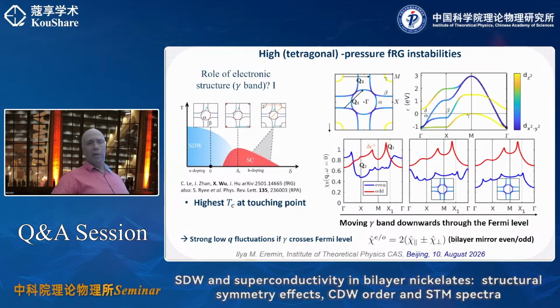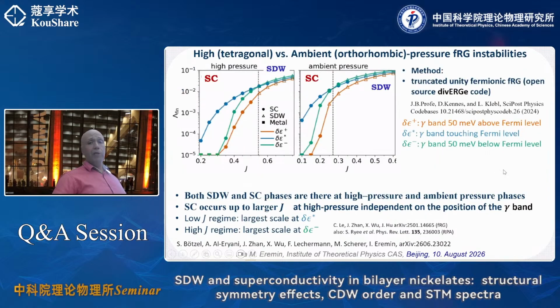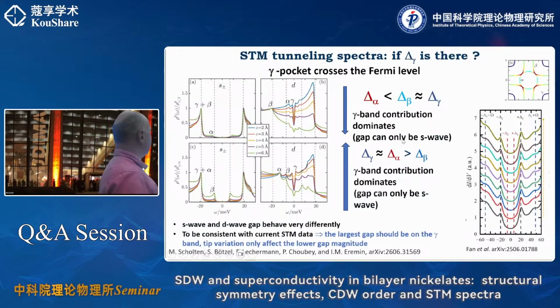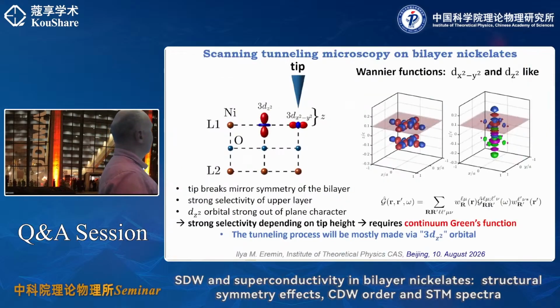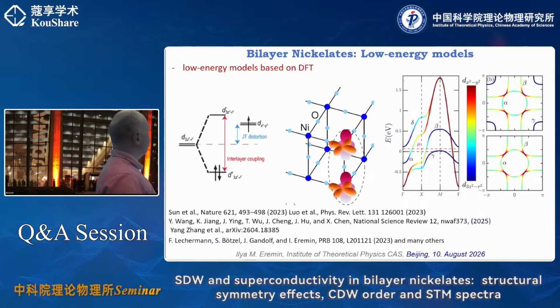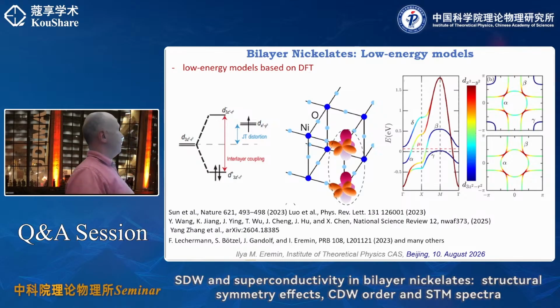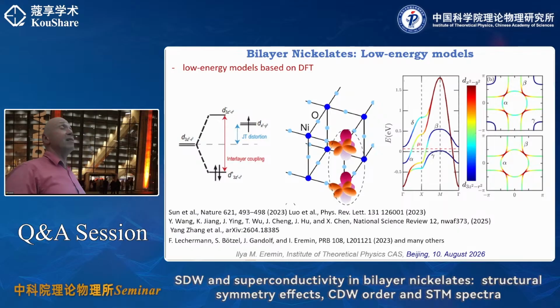I had this picture at the DFT level, right? You see that along this direction, the color is an equal mixture, if you want. So the z squared starts here, but then it comes back also here, because it has to come back here by symmetry, right? Yeah. So in this regard, I would say you can take both points of view. There is this proposal by Khaliullin, who is saying, look, z squared forms this triplon excitation, and this is how the pair forms, and then you have these two residual bands which participate, which have this coupling to this triplon excitation.